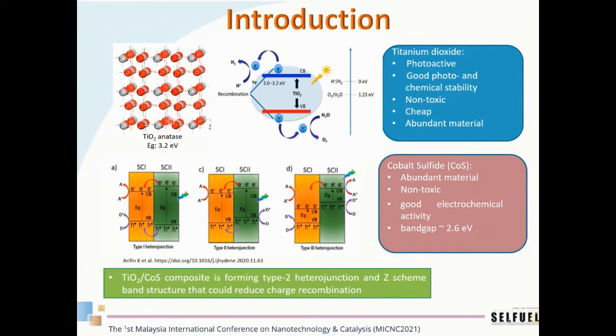As we know, the amount of UV energy is only around 4% of the solar spectrum. Meanwhile, the majority of the energy, which is visible light with an amount around 40%, cannot be utilized. The wide band gap also causes the photo-generated electron and hole to recombine easily. That's why the maximum photocurrent density TiO2 is able to achieve is only 1 milliampere per cm square.